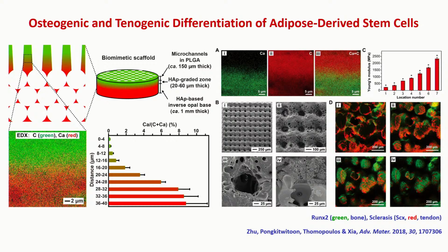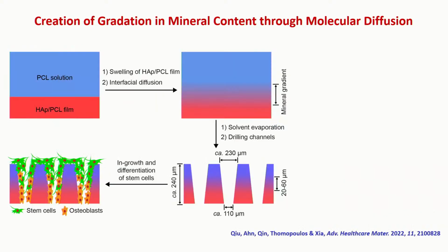And most recently, we further simplified this idea to fabricate these gradient scaffolds. We find that you can simply take a polymer solution, in this case PCL, and place it on top of another film that's made of a composite, right? It has hydroxyapatite and the PCL. You just put this together, you heat up a little bit, and well, no, not heat up, I'm sorry.